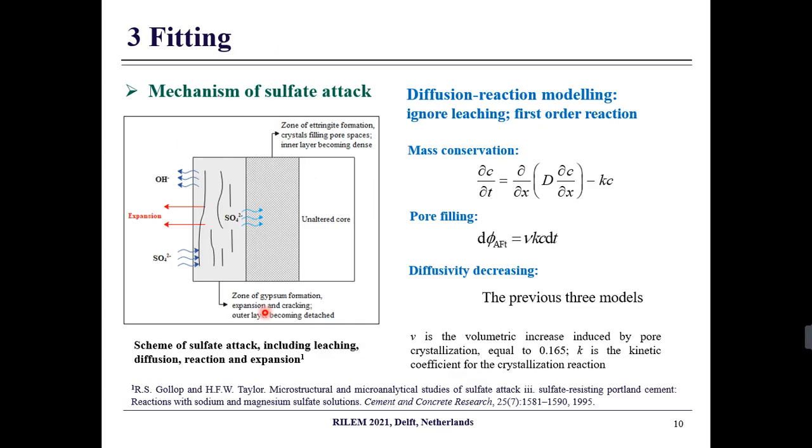Next step is to validate from existing experiments. However, only apparent and equivalent diffusivity can be found in the literature. In fact, the real sulfate diffusivity is very difficult to measure because the ettringite amount changes along the diffusing direction. So we have taken an indirect method.